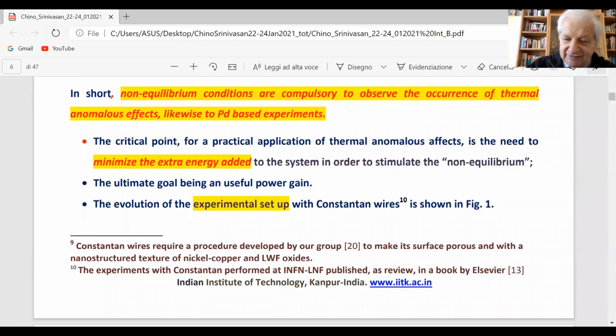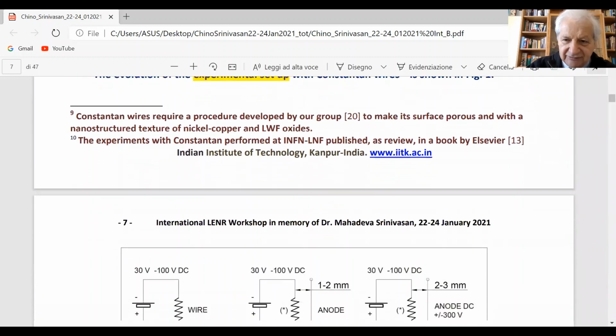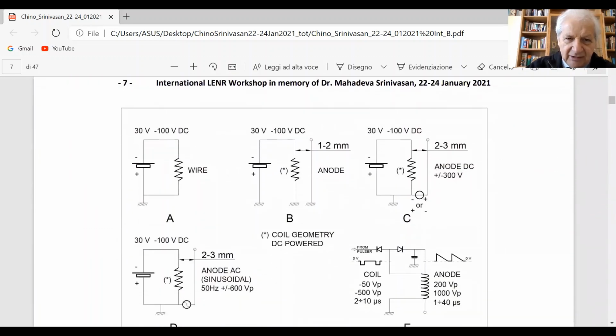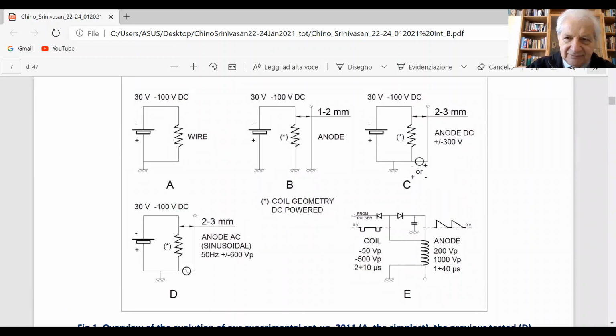We developed several experimental setups with the Constantan. This is a short review in this picture. At the beginning, just a wire, very similar to the palladium geometry. Later, we added a counter electrode at a very close distance, 1 to 2 millimeters. Later, the counter electrode was powered with DC voltage up to 300 volts to improve the Paschen regime.